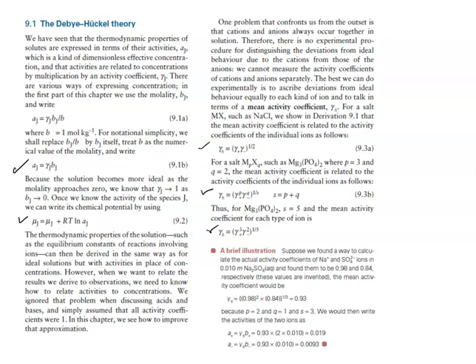Suppose we found a way to calculate the actual activity coefficients of sodium and sulfate ions in 0.010 molal sodium sulfate and found them to be 0.98 and 0.84 respectively. And these are contrived values, just so you know. The mean activity coefficient would be equal to 0.98 squared times 0.84, and then that entire quantity would have a cube root. So the overall value would be 0.93. This is because P equals 2, Q equals 1, and S equals 3.